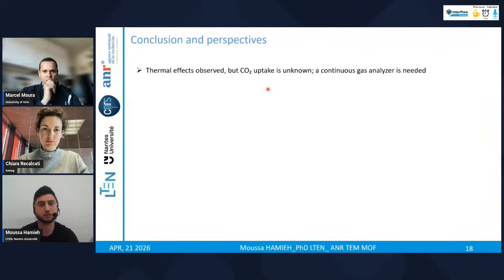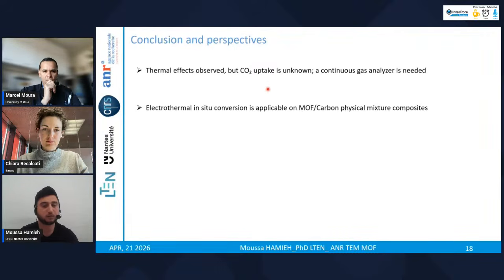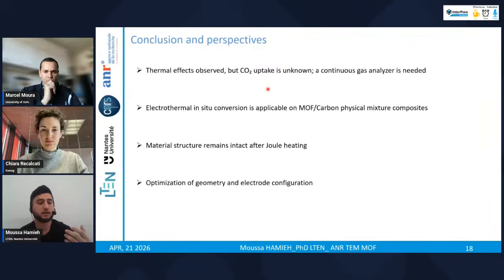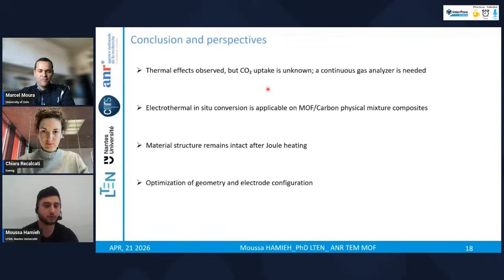and the CO2 uptake. Second, we have demonstrated that electrothermal conversion is applicable to the MOF carbon composites, enabling efficient heating for the desorption. Third, we showed that the material structure remains intact after multiple Joule heating cycles, confirming its stability by X-ray diffraction. As perspectives, future work will focus on optimizing the system design, particularly the geometry and the electrode configuration, to enhance the current distribution and the heating efficiency during the desorption step. And at the end, we will also explore coupling with direct solar energy for the thermal regeneration.